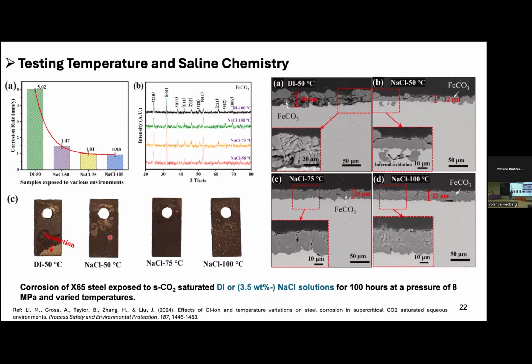And then I said, okay, when my student presented this data to me, I said, repeat it. I don't want to present something and then look like an idiot. And then they repeated everything and it was the same. And then we went back to see the compact layer, the iron carbonate layer formed in this environment. Apparently, when you have sodium chloride versus DI water, you have a more compact and more dense layer. Same for the temperature. When you increase the temperature, your layer formed very quickly and is also more compact.